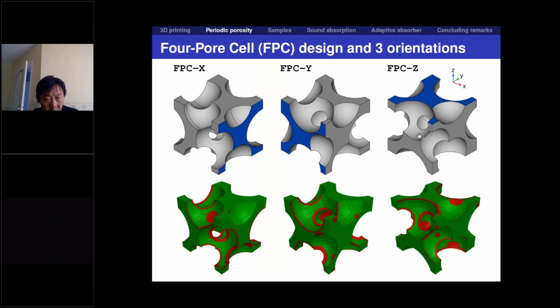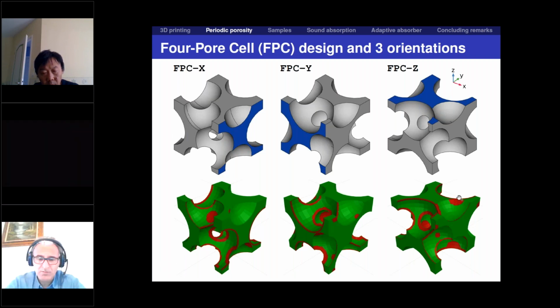First I checked these periodic unit cells with my slicer software for one of my FDM printers, and the size of this cell is 5 millimeters. You see that using my software I can check if this cell will be printed correctly. And unfortunately we have a lot of red areas, which means that here, for example, we shall have an additional window which is not present in the original design. This window will be smaller than the original one, a little bit rough perhaps.